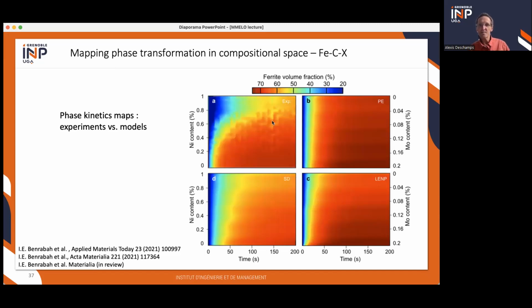And here we're showing this in maps of nickel content in Y, time in X, and ferrite fraction in color. And so this is the experimental data. And this is a solute drag model, and these are LENP and PE. And well, the fit is not perfect. It tells you probably that you could improve the model still. It's much better with solute drag than with the other models.